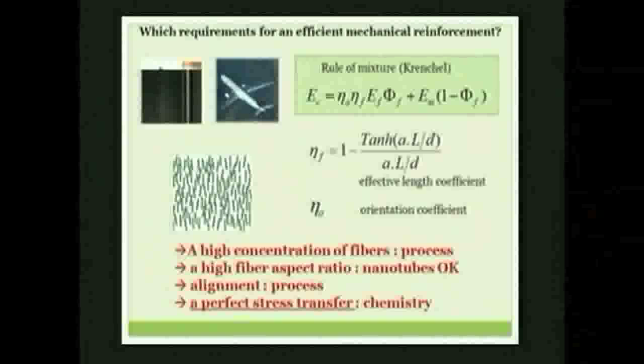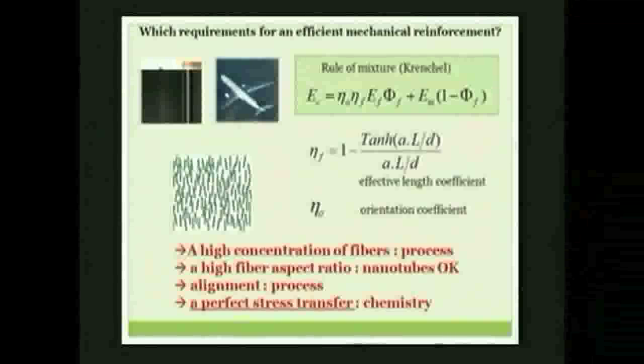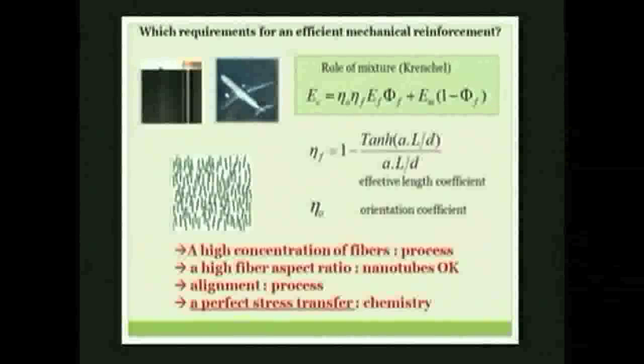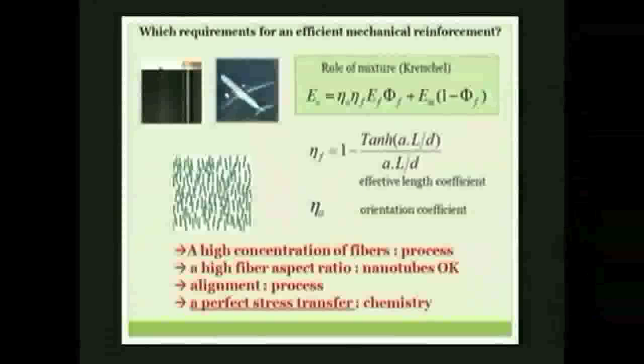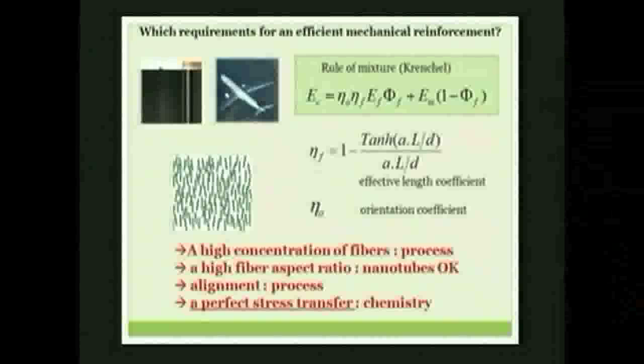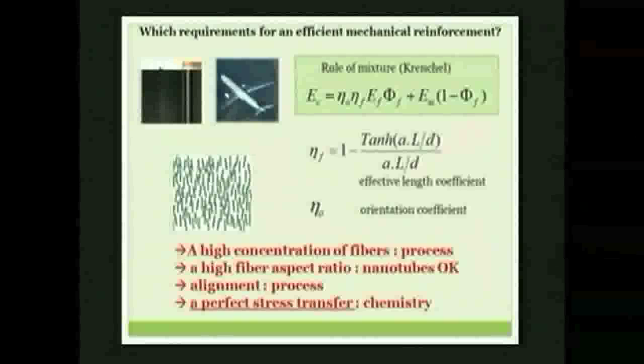Here, phi_f is the fraction of nanotubes that you will put. And these two parameters, eta_0 and eta_f, I'm going to explain what they mean. Eta_f, just keep in mind that the effective length coefficient says that the nanotubes have to be as long as possible to induce a good reinforcement. Okay? This coefficient goes to 1 if the aspect ratio of the nanotubes is very high. Okay? Eta_0 is the orientation coefficient. It varies from 1/6 to 1: 1/6 if the nanotubes are completely disoriented, and 1 if they are perfectly oriented within the composite.